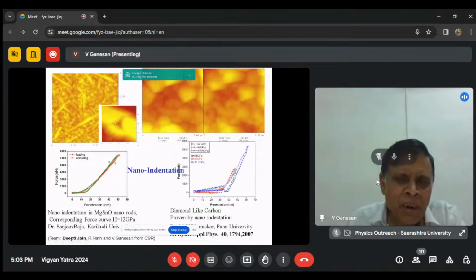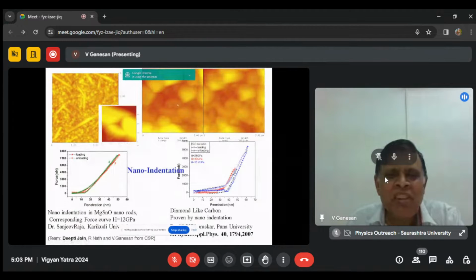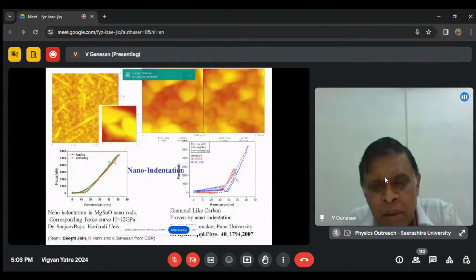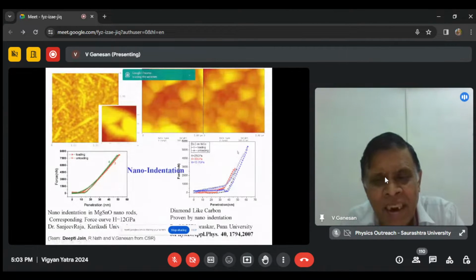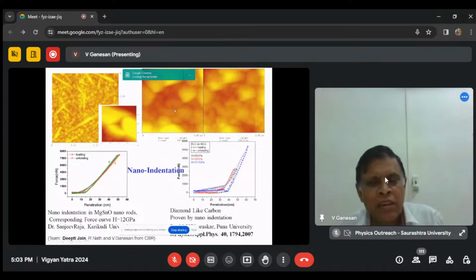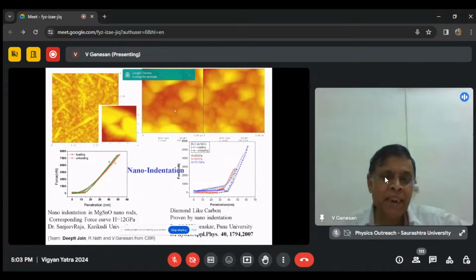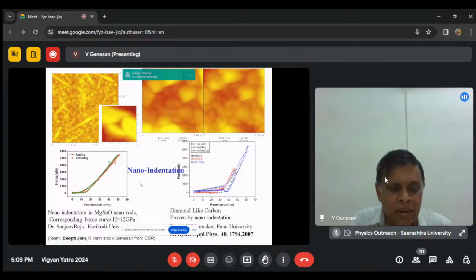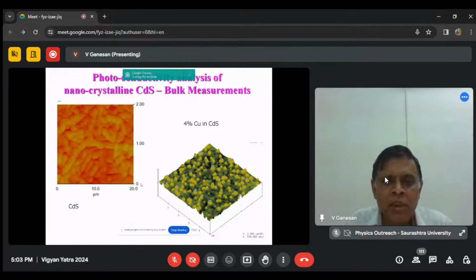You can make the measurement even for a thin film where you can't make an indentation. Still, the force curves can be measured, because the cantilever will bend and yield when the hard surface is there. For example, if you take a finger and put it in water, it will go inside. But if you put it on the table, your finger will bend. The bending of your cantilever will tell you how hard your surface is. And this has been done. We have done it on very interesting nanostructures, and a lot of good papers have come.